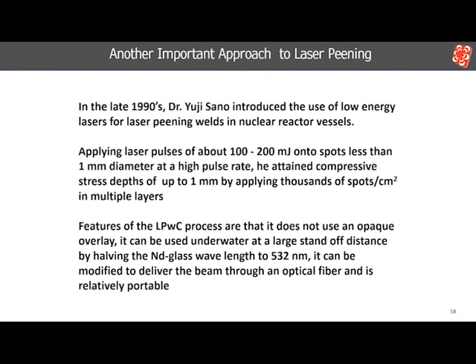Features of the laser peening without coating, or LPWC process, are that it does not use an opaque overlay. It can be used underwater at a large standoff distance by halving the neodymium glass wavelength to 532 nanometers. It can be modified to deliver the beam through an optical fiber and is relatively portable.